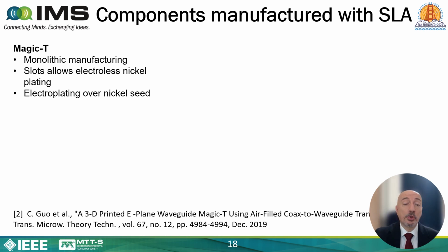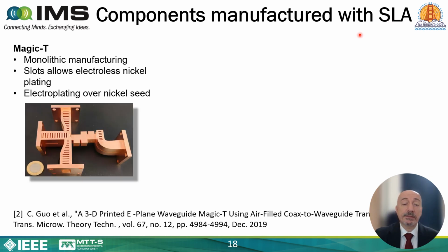I would also like to show you this Magic-T manufactured by using SLA. Well, this is not from my group, this is from another group, and you can see more details in this paper. But what I want to show here about this structure is that this is obtained by using electroless nickel plating, and indeed they were able to manufacture it monolithically. This is very interesting, but unfortunately, in order to allow the liquid to go inside the structure and in order to allow the metallization, they put a lot of slots in these waveguides, as you can see.